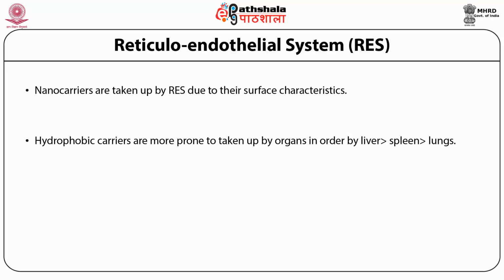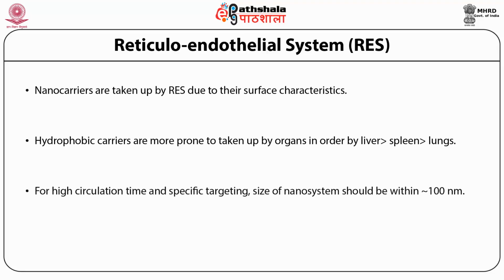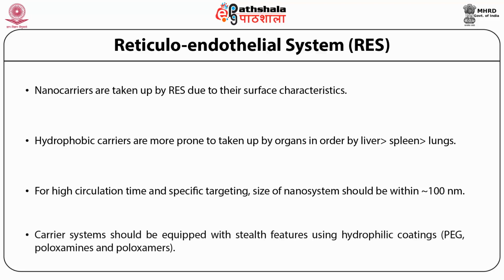Further, for high circulation time and specific targeting, the size of the nanosystem should be within 100 nanometers for the nanocarriers. The carrier systems should also be equipped with stealth properties by using polymeric coatings, which are hydrophilic based coatings made up of polyethylene glycols, poloxamines and poloxamers.